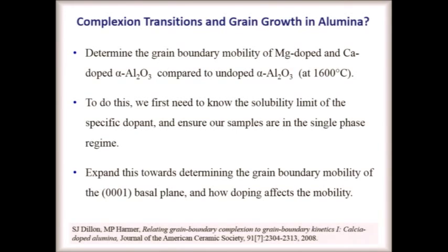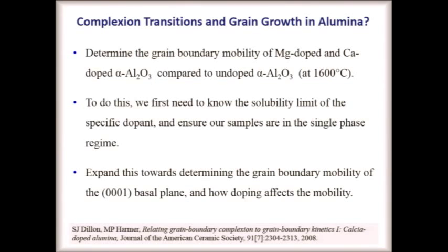So, based on what I explained yesterday, if we're above the solubility limit, if the dopants or impurities will go to the grain boundaries in order to reduce the grain boundary energy, then they'll go there. We have the driving force for them to go. Then the question is, how do they influence the rate of the mobility of these same grain boundaries? But in order to do that, we need to clarify if we have precipitates. By the way, we also have to clarify if we have pores, to prevent pores from being influential.